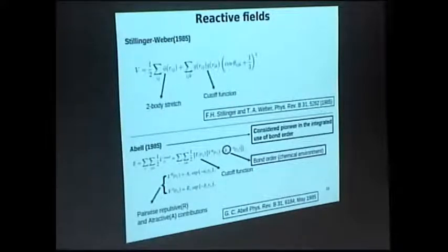Okay. Then if you have some big distance between two carbons, you have a bond order of 1, that would be the sigma contribution. Then if you have some shorter distance, you have sigma and a pi contribution, making a double bond. And that is controlled by the bond order parameter that we calculate. And then you can also have the triple bond order, and we will see that later. But this is the idea.